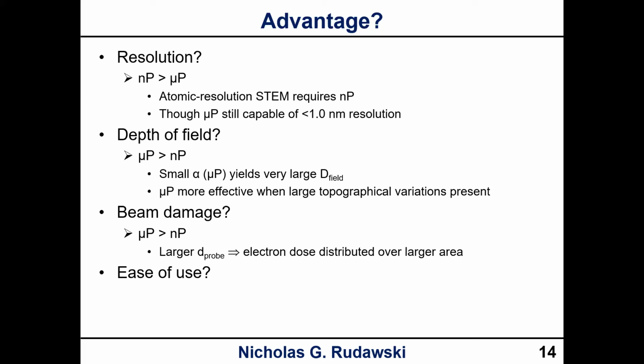If you have a situation where you're worried about beam damage, you have a larger probe in microprobe. So if your current is the same, you're going to spread that dose over a larger area. So, in principle, damage is going to be less of a concern. And then we saw just a minute ago how it's easier to set up microprobe versus nanoprobe.